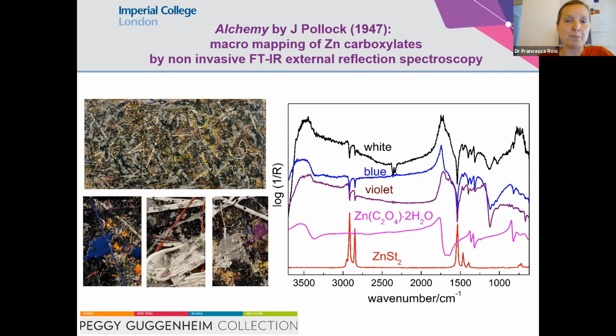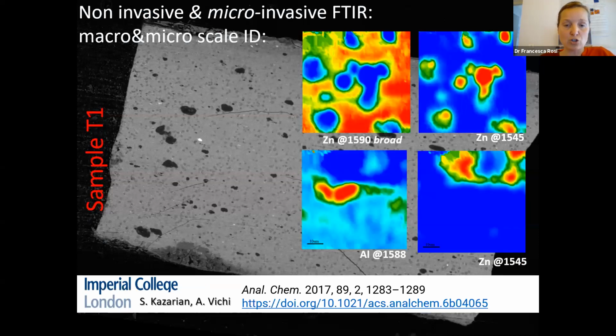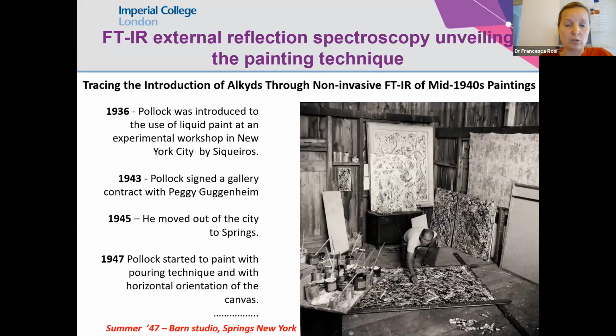material, as we did for the masterpiece of Pollock, Alchemy, in which an extensive non-invasive study through FTIR spectroscopy enabled us to underline the presence of zinc oxalate for the blue phthalocyanine-based pigment, for the zinc oxide and titanium white, and for the manganese purple paint. This enables us also to guide and to select representative samples for deeper investigation of such a mechanism of degradation. This work, for example, we have carried out in collaboration with Prof. Sergey Kazarian, and maybe he will detail better what is possible to do at a micro scale, working with FTIR for revealing information regarding degradation material or micro heterogeneities at a microstructure level.